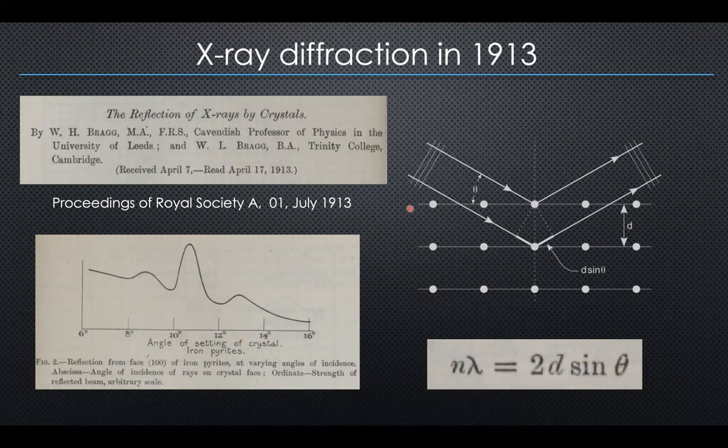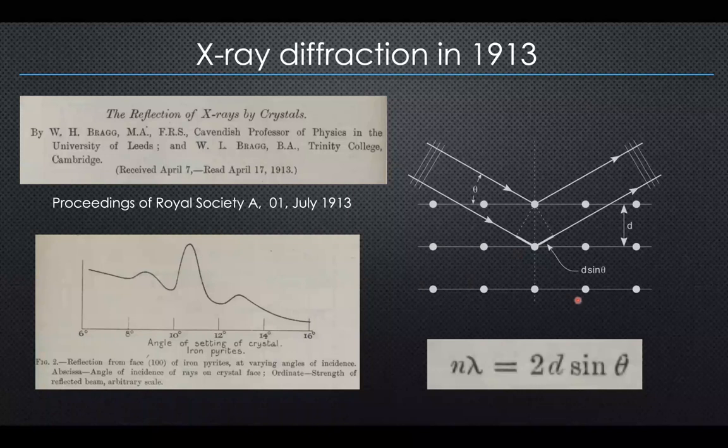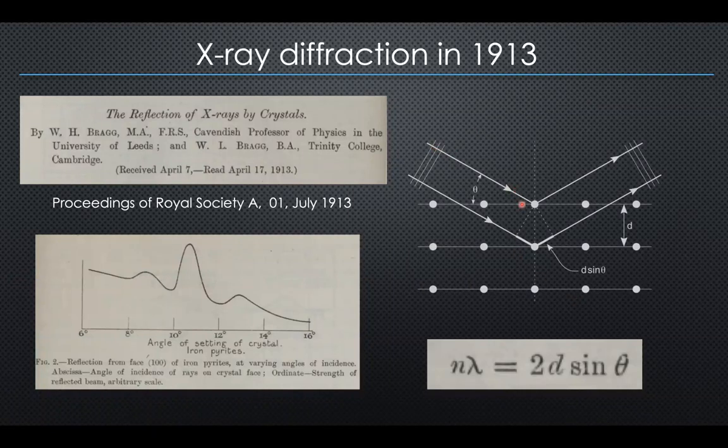The model was that my atoms are forming a lattice, and if my incident angle and reflection angle are such that I'm getting a peak, that should tell me about the distance between the atomic planes. This is an example of forward modeling. In all forward modeling, we guess what kind of arrangements of scatterers or atoms are in real space, produce what scattering intensity they would amount to, and try to match that scattering intensity with the data by changing the parameters of the model.